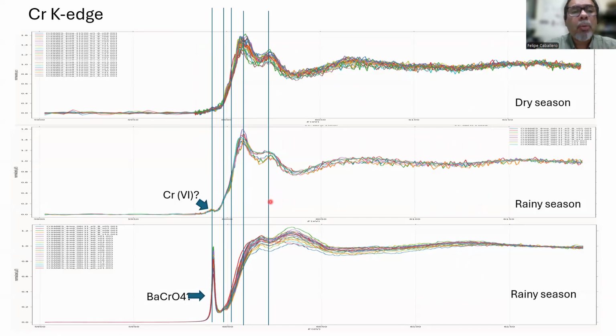So in the case of chromium, you see we performed a lot of spectra. At least 20 spectra were performed in different parts of the dry season sample. You can see that all the spectra are practically the same, have the same shape, which indicates that all the chromium is in almost the same chemical form.